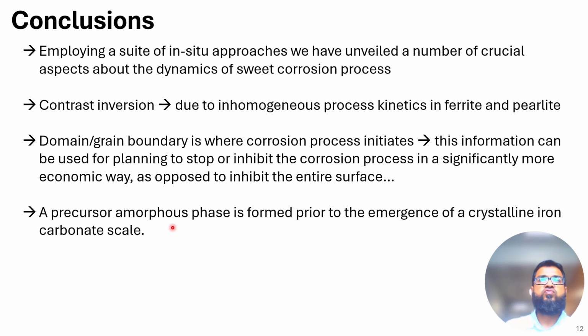And from our SAXS and WAXS experiment, we have shown that the precursor formed is actually amorphous, and then it eventually transformed into a crystalline iron carbonate. And